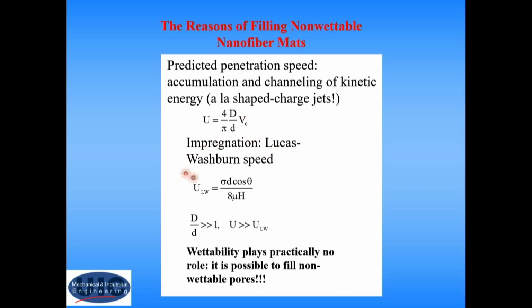And if you compare this velocity with the so-called Lucas-Washburn speed, which is the velocity of penetration by wettability, for example, if you have a fully wettable membrane which sucks water in by wettability, this result describes how fast this suction goes. This is a kind of diffusion process, and this result essentially relates the penetration to surface tension, because the surface tension here is not equal to the liquid-solid surface tension pulling the liquid in, but it's equal to the liquid-gas surface tension, so it's a misleading factor standing here, but I'm explaining why it's like that. And it's also inversely proportional to the viscosity of the penetrating fluid, and obviously the thickness of the mat.